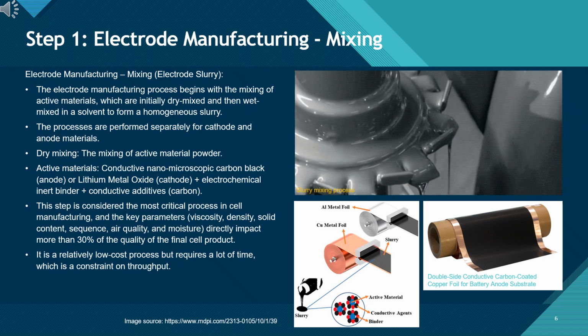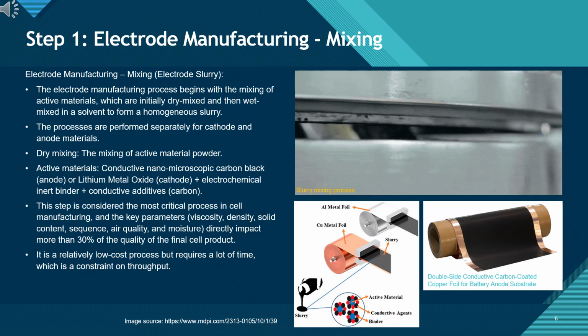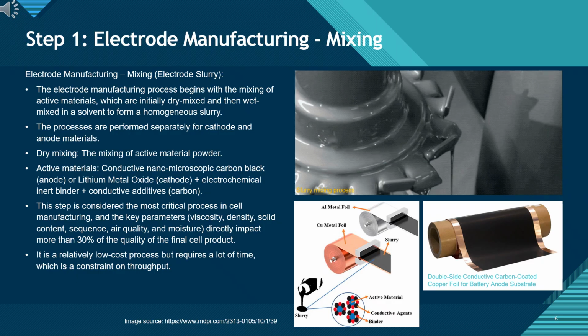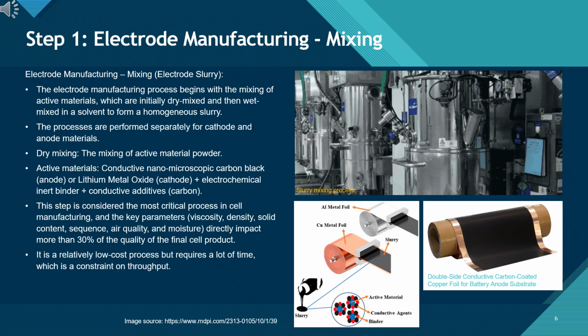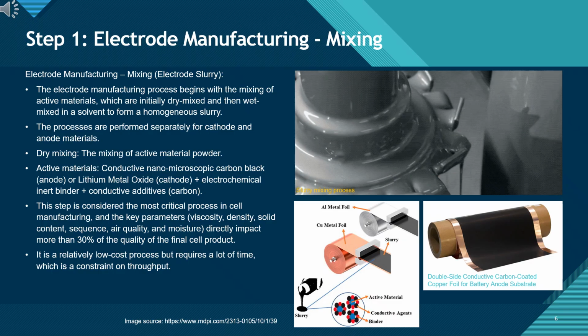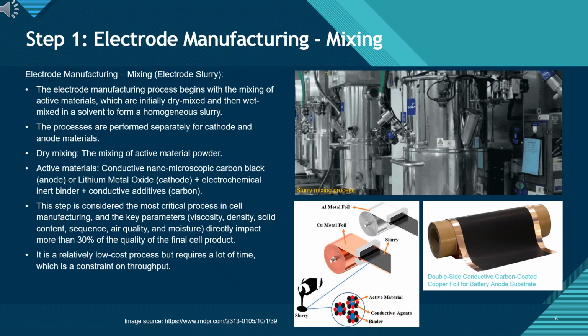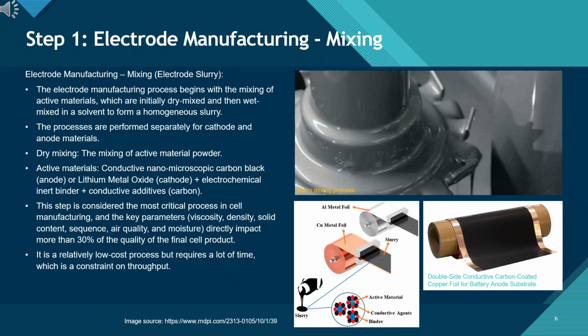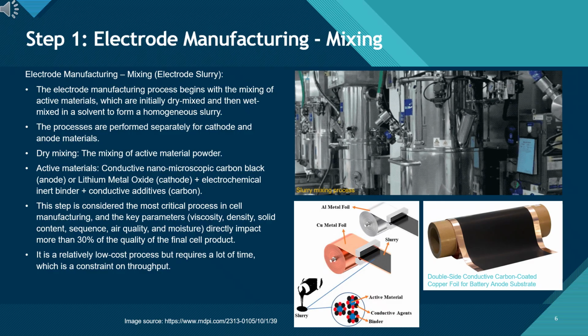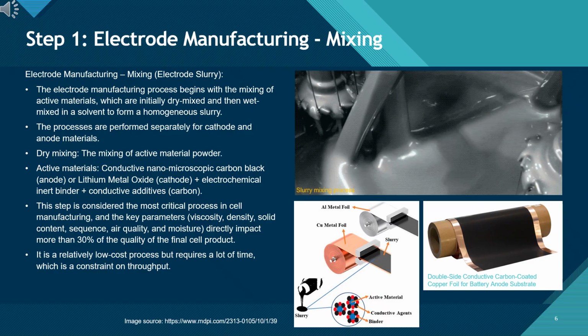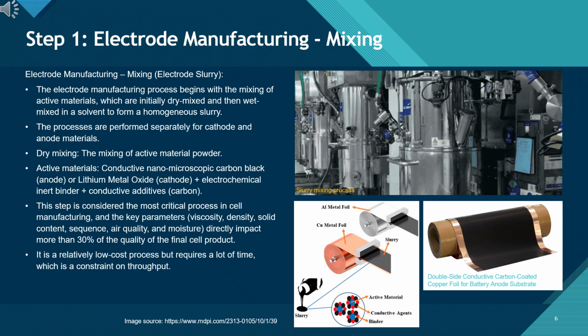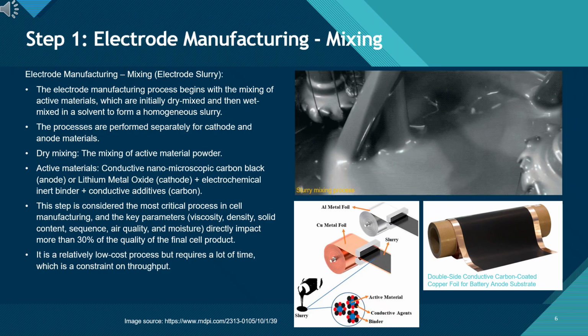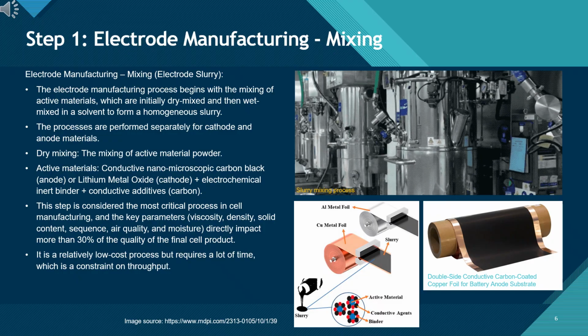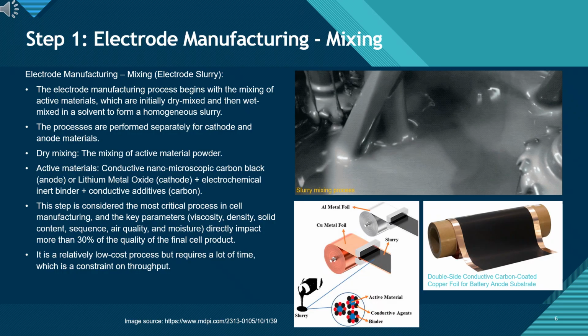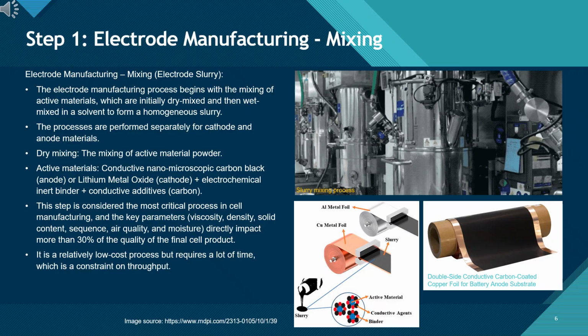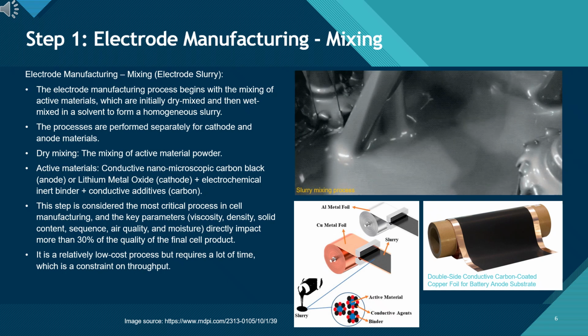together, keeping everything stable. This step may look straightforward, but it is actually one of the most critical processes in cell manufacturing. Parameters like viscosity, density, solid content, and even air quality and humidity must be carefully controlled. Mistakes here carry forward and can affect more than 30% of the final battery quality. Mixing is relatively low cost compared to other steps. However, it is time-consuming and often limits the overall production speed. That's why consistency, monitoring, and discipline in this step are essential for the whole line.